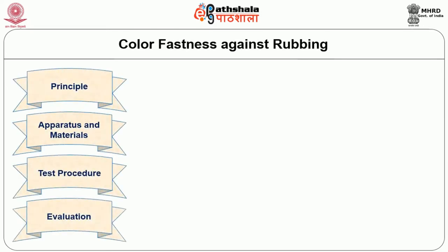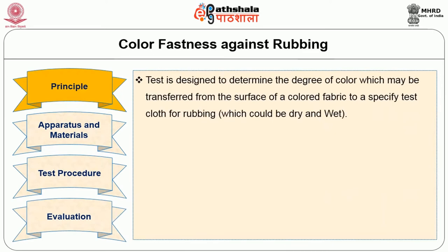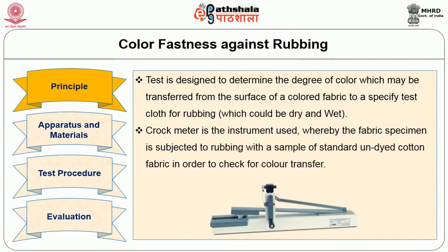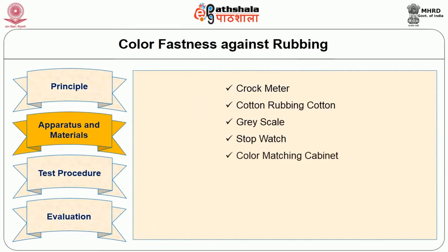Next is color fastness against rubbing. The principle used is to determine the degree of color which may be transferred from the surface of a colored fabric to a specified test cloth after rubbing, in dry and wet conditions. The crockmeter is the common instrument used, whereby the fabric specimen is subjected to rubbing with a sample of standard undyed cotton fabric in order to check for color transfer. Apparatus and materials used for rubbing fastness: crockmeter, cotton rubbing cloth, grayscale, stopwatch, color matching cabinet.